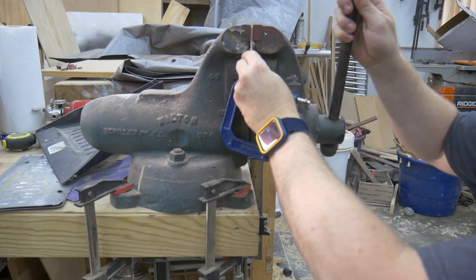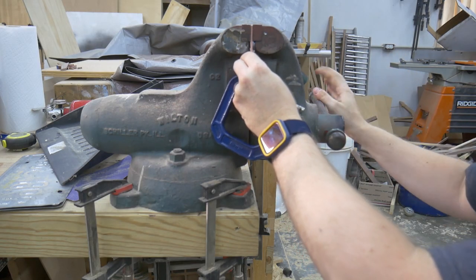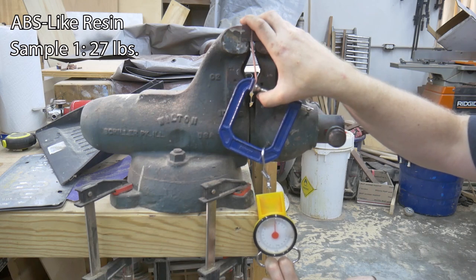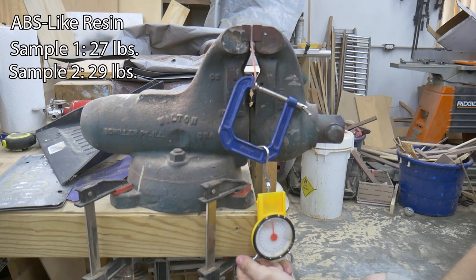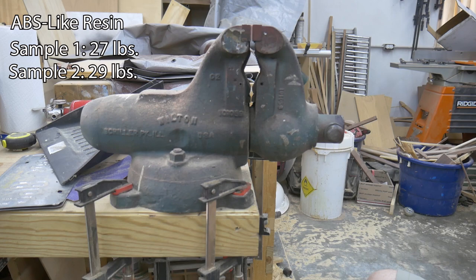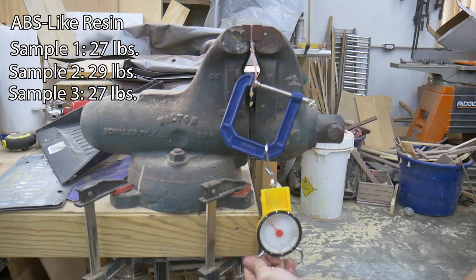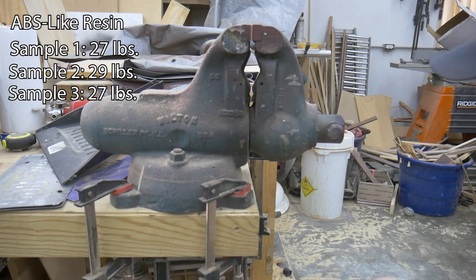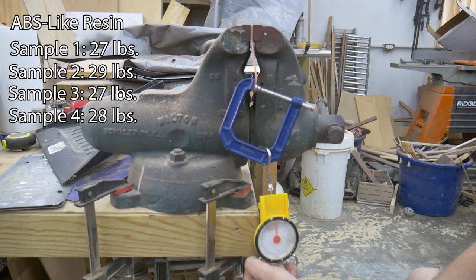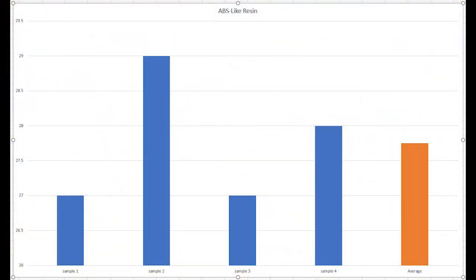Let's see how the ABS-like resin performs in the same test. Sample 1 failed at 27 pounds. Sample 2 failed at 29 pounds. Sample 3 failed at 27 pounds. Sample 4 failed at 28 pounds. The average strength of the ABS resin after testing is 28 pounds. That is a 38% increase in strength over the standard resin. ABS resin takes this round.